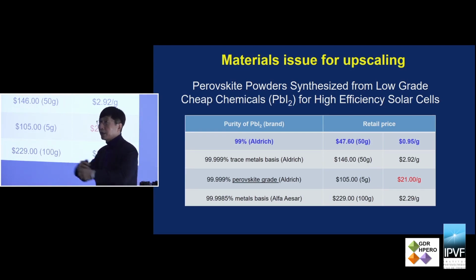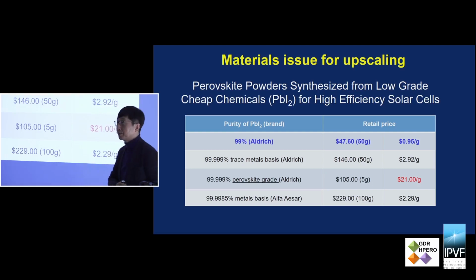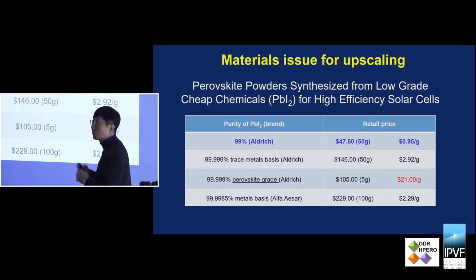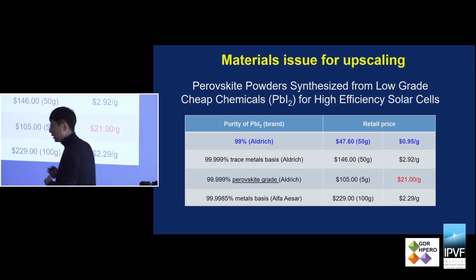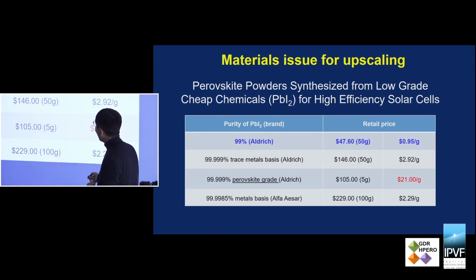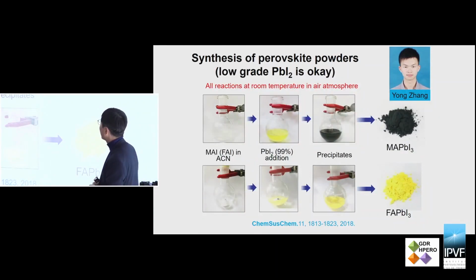Also, the precursor mixture has some kind of aging effect, so you have to control the precursor solution well. Therefore, it is not suitable for large-scale upscaling of the process. So we thought that if we make the perovskite powder, then we can reduce the cost and probably increase the efficiency and the reproducibility of the performance. So we use the low-grade PbI2, and also recently we prepared the PbI2 from lead nitrate, to decrease the cost even further. So this is